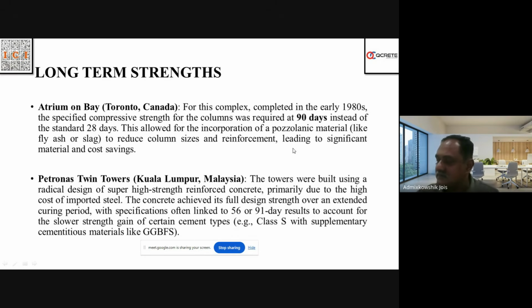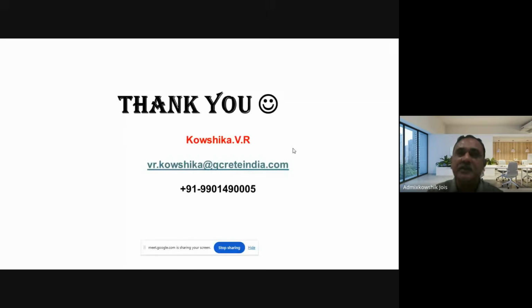Similarly, for the Petronas Twin Towers, the specification was often linked to 56 or 91 days, to account for the lower strength gain of certain cement types. So BS 8500 very clearly says this, and there are other codes also. And now we have a lot of data in India also that long-term strengths are acceptable. So what we can say is that a low cube strength is not a low cube strength unless it is investigated, unless it is properly studied. In most cases it can be apparent strength and it may not be intrinsic strength. So we need to be judicious in taking a final conclusion on whether the concrete is acceptable or not.